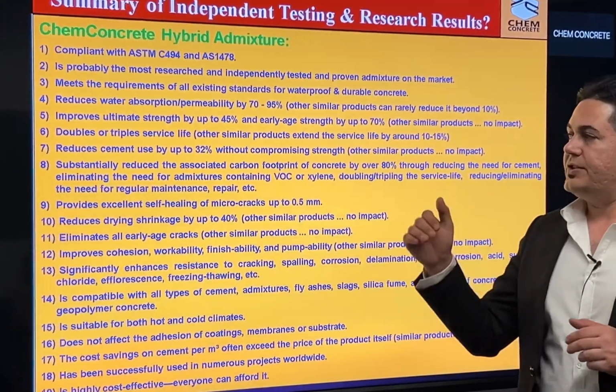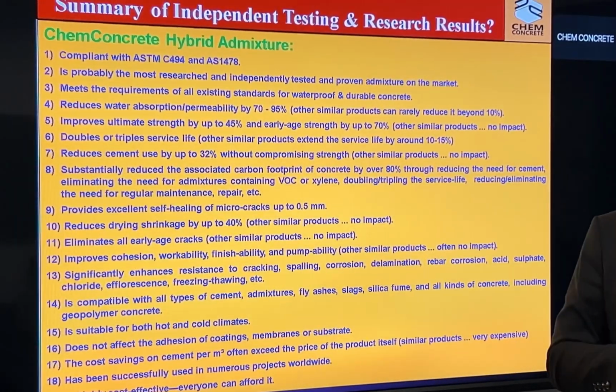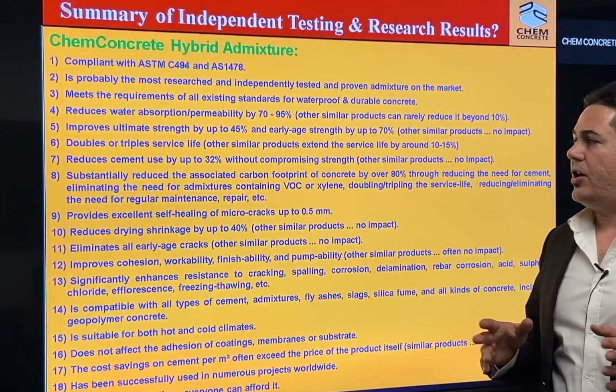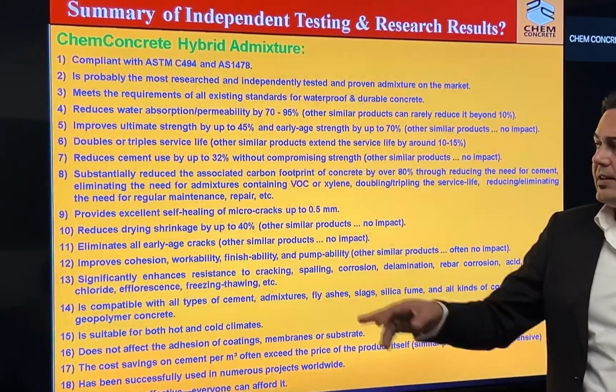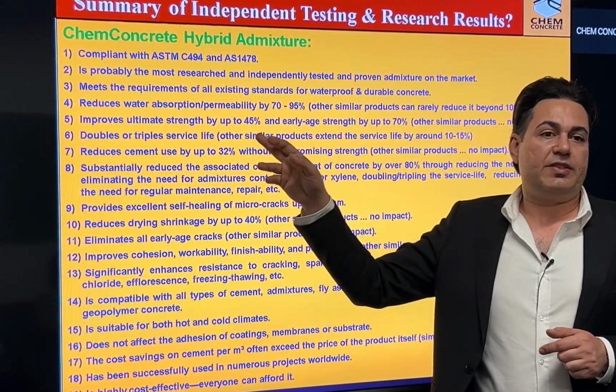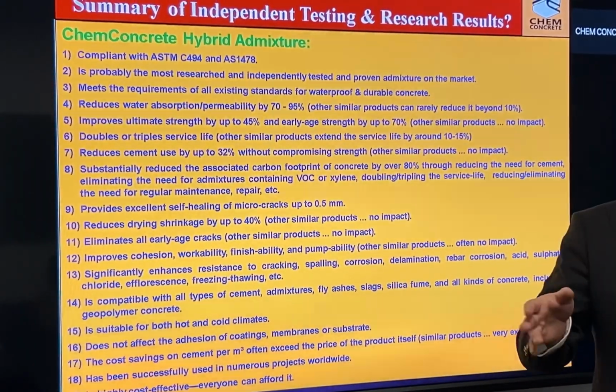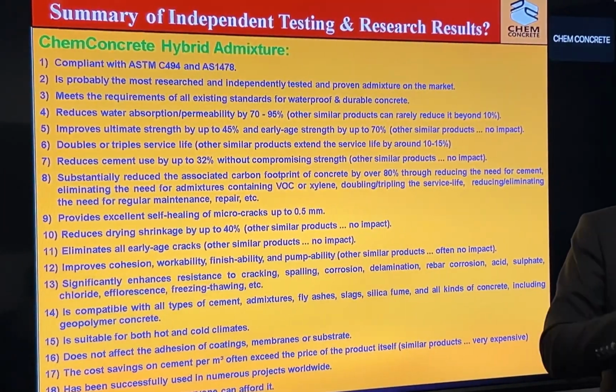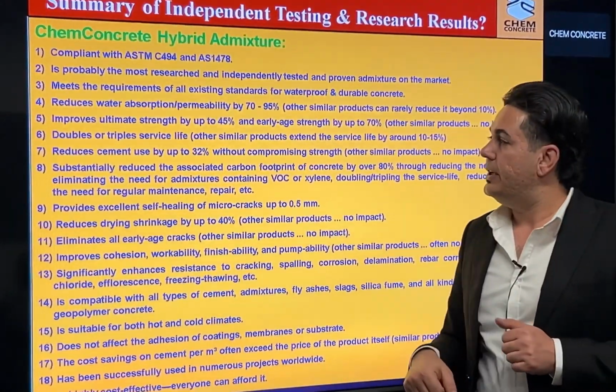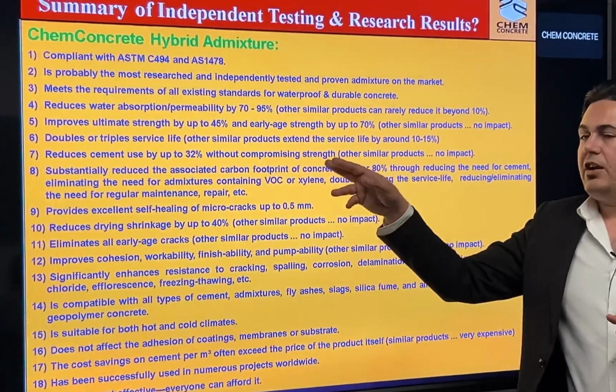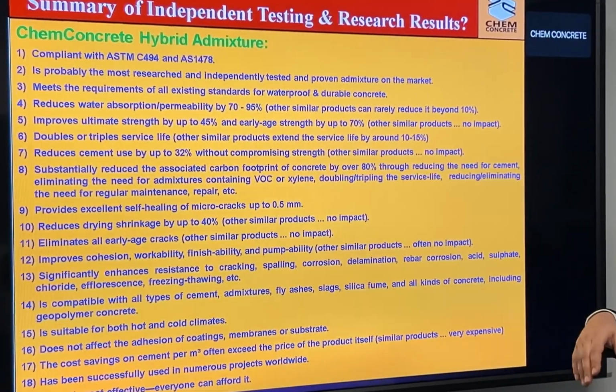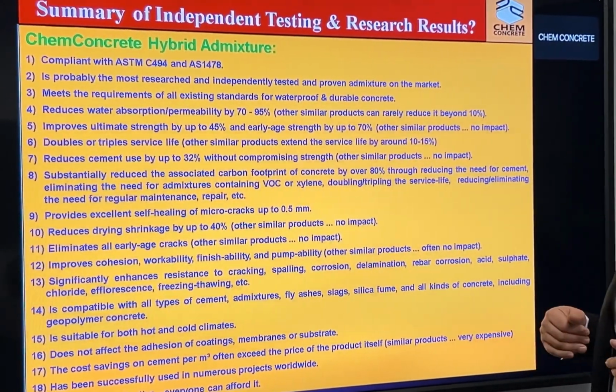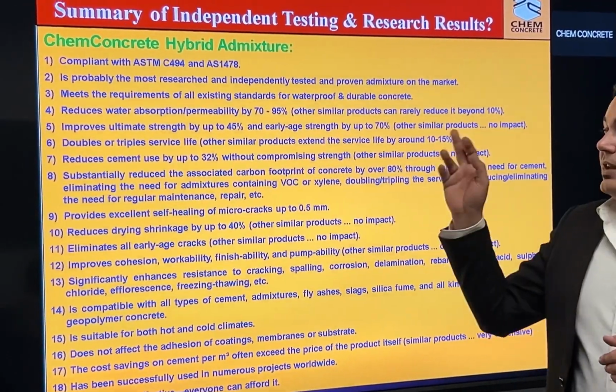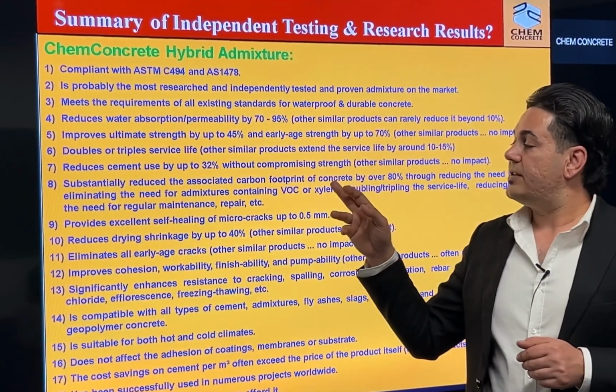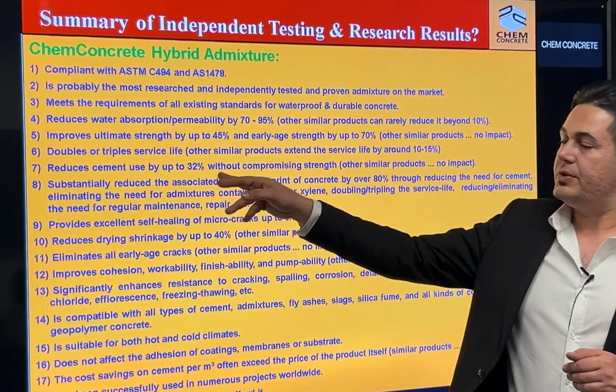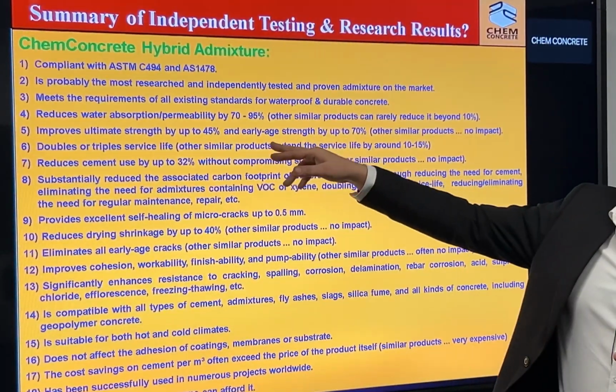Well, yeah, the test results, long-term durability monitoring, as well as life cycle assessment on these test results have also shown that the product can double or triple the service life of concrete, again depending on whether the minimum dosage is used or the highest recommended dosage is used. So other similar products have been proven to extend the service life usually by around 10 to 15%.